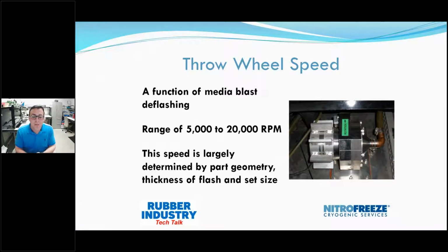That sweet spot is usually, let's say your throw wheel speed range on your machine is 5,000 RPM to 10,000 RPM, it's good to start in the middle. With our machine in particular, we've got 5,000 to 20,000, so we're right around 12.5. That's where we like to start when we're doing samples.